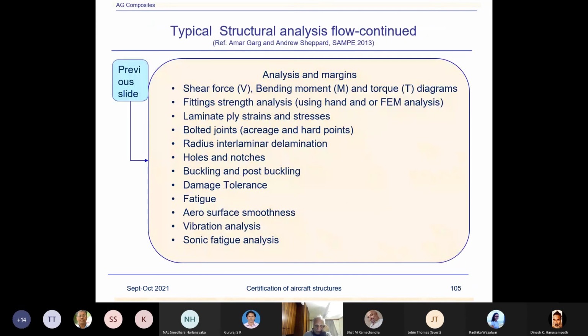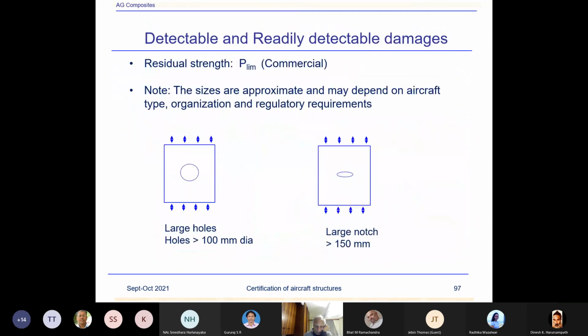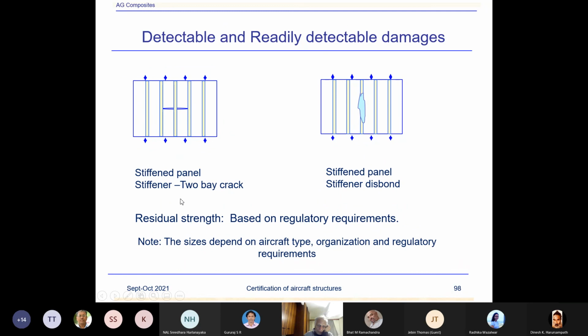Let me just go back. When you are trying to analyze this, it's a layup. So damage normally will be considered initially, say here, this much damage. Then I'm loading it, and the damage should be able to propagate right up to this, but beyond this it is not allowed to propagate. Normally we consider that the damage should deviate and go as delamination, so that the residual strength capability we get after this propagation is like a get-home load capability, two-bay crack, or limit load.